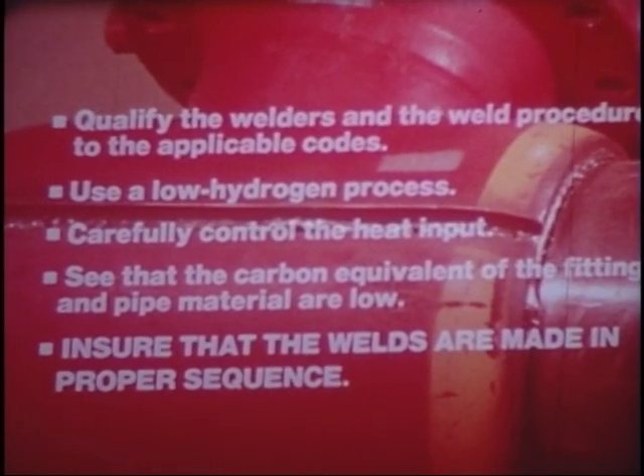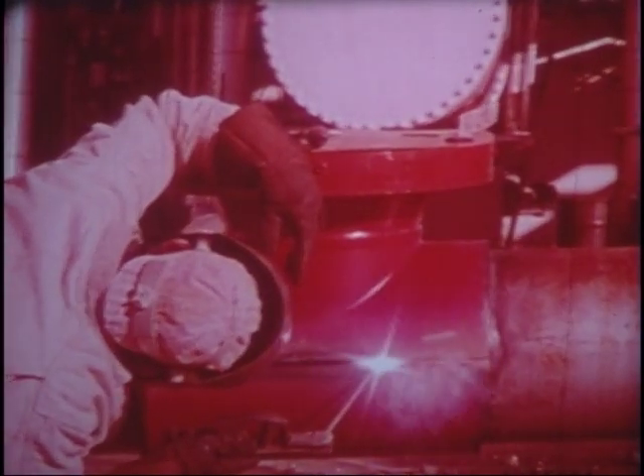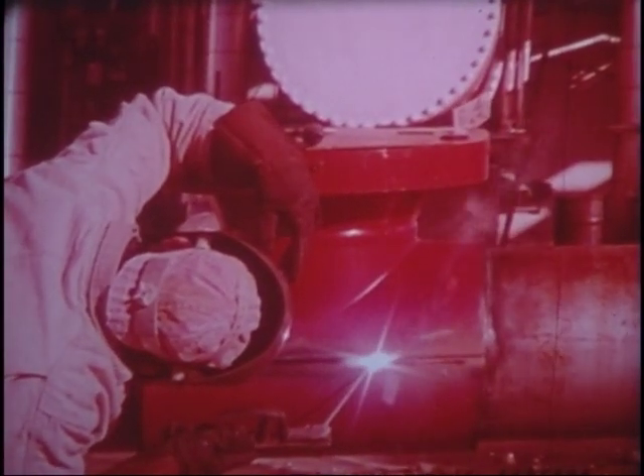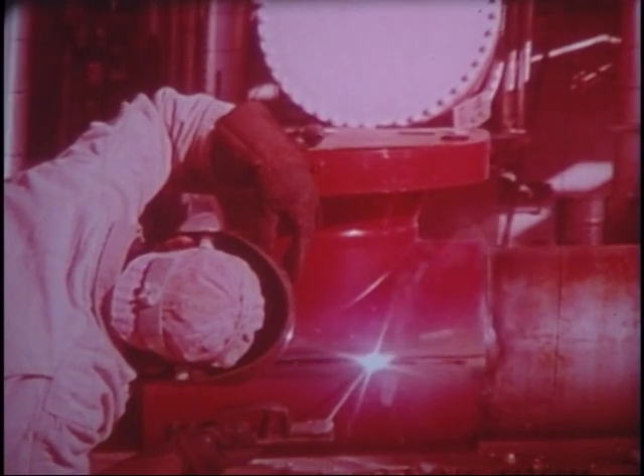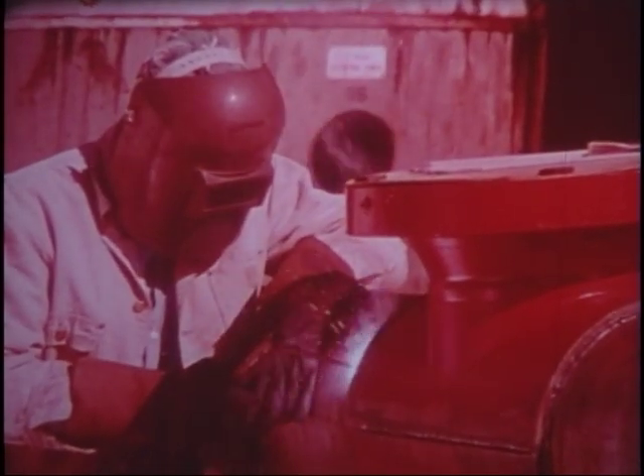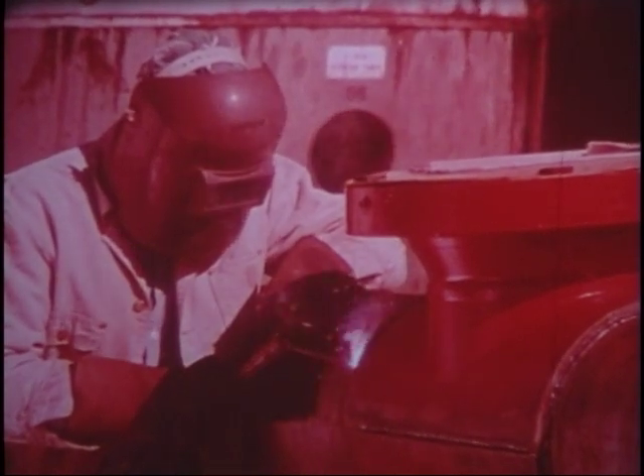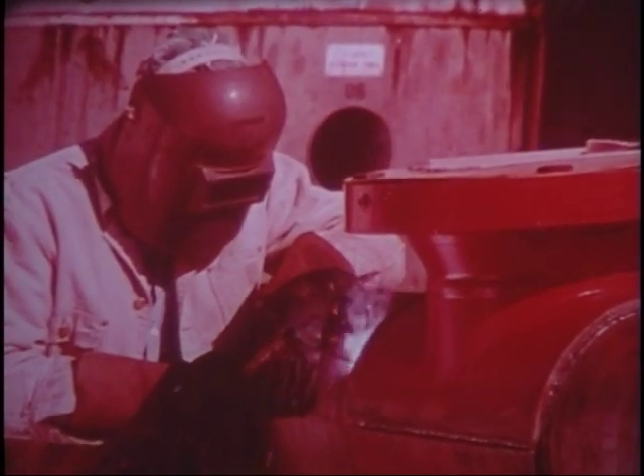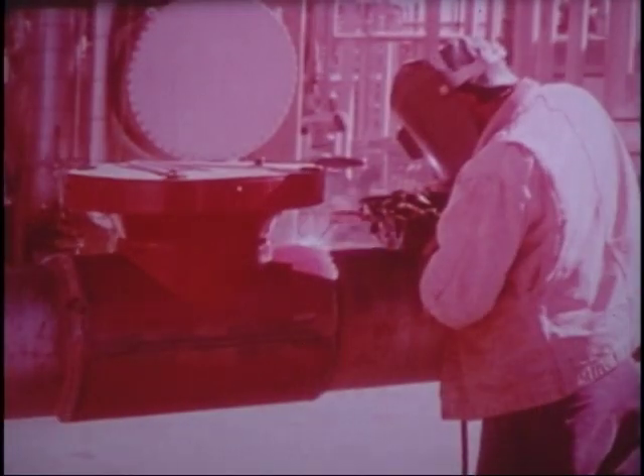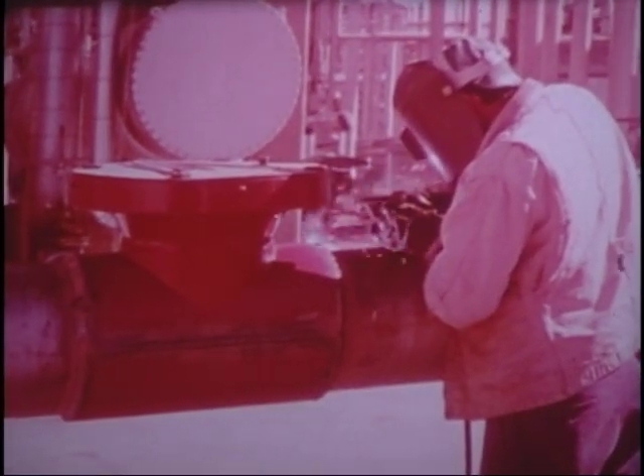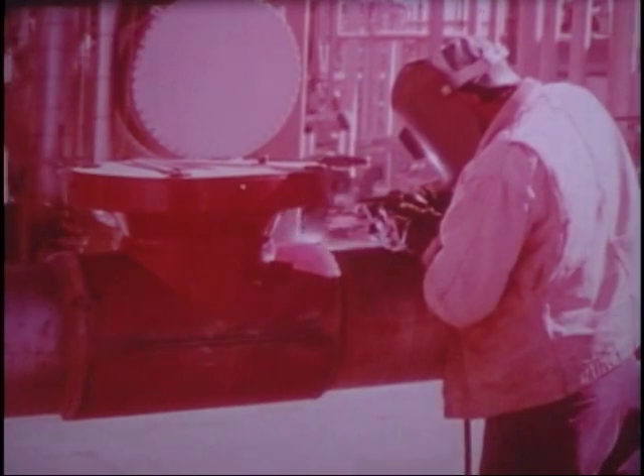ensure that the welds are made in the proper sequence. Longitudinal welds are done first and must allow a suitable weld gap to prevent fusion of the fitting to the pipe. Next, a circumferential weld is made on one end of the fitting, followed by a circumferential weld on the other end. Avoid overfilling the end circumferential fillet welds. A fillet weld size of about 1.5 times the pipe wall thickness is considered sufficient.